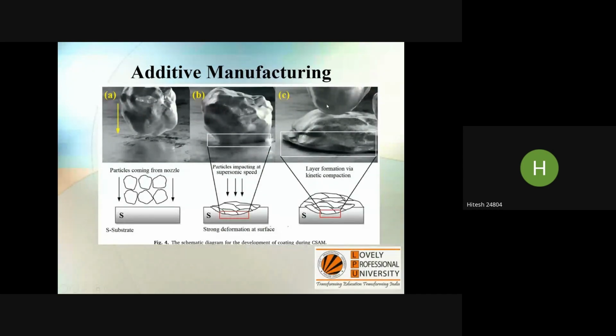Here you can see, because another particle is also coming after this particular particle. So a number of particles are coming and striking the surface to form a layer. So this layer is very compact, because the powder particles are continuously coming out of the nozzle with very high velocity, striking the surface and getting plastically deformed to form a layer one over another. So in thermal spraying, we call this layer by layer formation, and one layer is also known as a splat. So this is also called splat by splat formation.